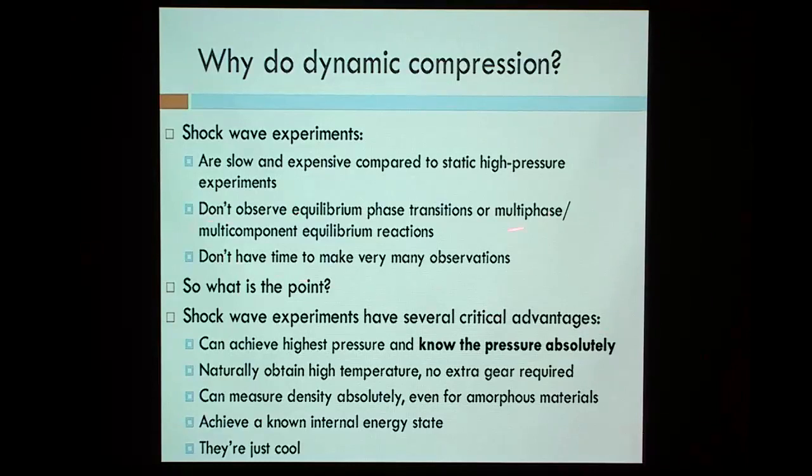You can't really see equilibrium. If you're interested in phase transitions, they're not going to happen at the equilibrium boundary in a shockwave experiment. And so you shouldn't necessarily use shockwave experiments to find equilibrium phase transitions, but you do get phase transitions and you can study high pressure phases. You can't really do petrology. You can't really do multi-component, multi-phase experiments. There just isn't time for all the phases to see each other.